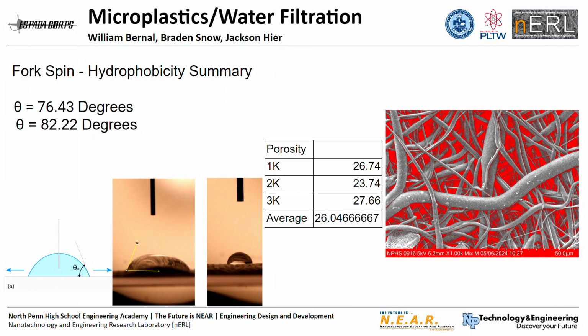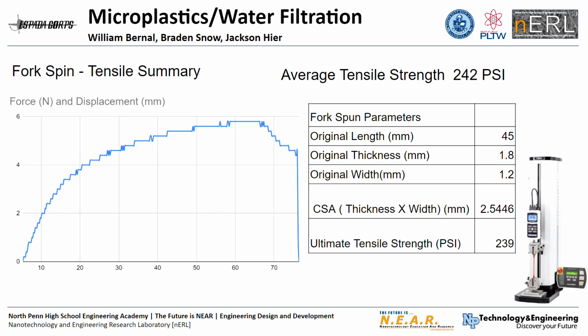When looking at porosity, we were able to get it to 26%, which was our best of the entirety of our tests, and turned out to be very effective. Now, looking at its tensile strength, although it wasn't the highest, it was still definitely enough that it would be able to withstand any type of water pressure in any type of household. When we finally looked at how our fork spinning filter worked out, we ended up coming up with 86.1% of our total plastics filtered through. As you can see in the water right there, there's still a little bit of particulate, but at the same time, it's much better than drinking all of them.